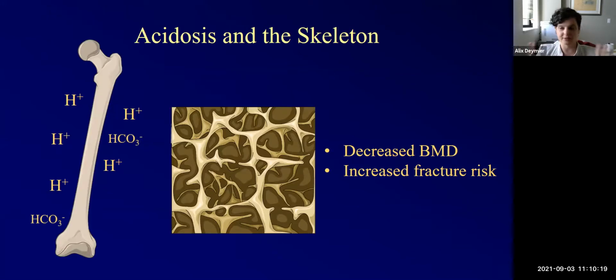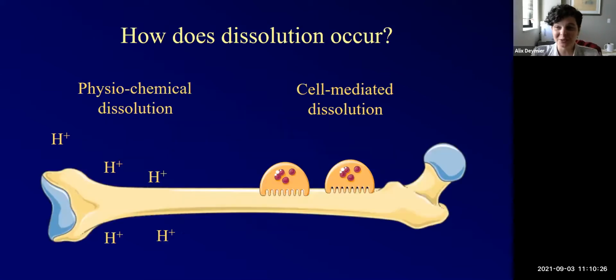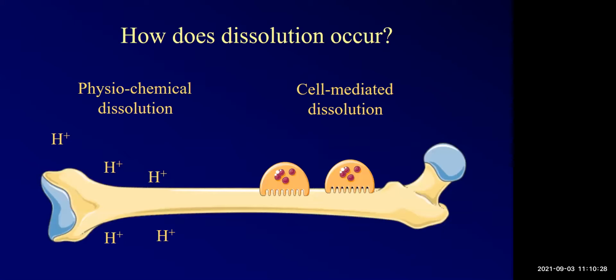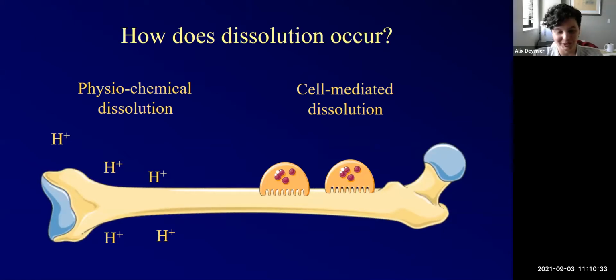Now the question here isn't, does this happen? We do know that it dissolves and that it does all these things. The question is, how does it happen? Now, the dissolution mechanism of bone has been hotly debated for a very long time. Seems like such a simple question. And there's really two main camps. On one side, you have the physiochemical dissolution people. They say you'd have acid in the body, the bone comes into contact with this acid, and essentially you're just dissolving these crystals, which are primed for dissolution because of their composition.